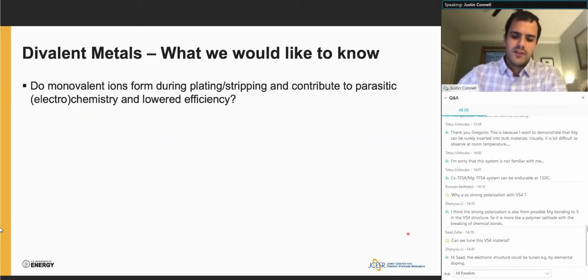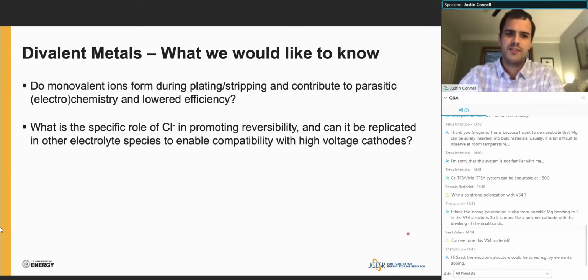Now, with all of this insight, there's still a lot of questions we'd like to answer. In particular, there's been a lot of theoretical evidence that monovalent ions form, but thus far we haven't really been able to show experimentally that they're actually present. So we'd like to know, do these monovalent ions form and contribute to parasitic electrochemistry, resulting in lower efficiency? In addition, we'd really like to know, what's the specific role of chloride in promoting reversibility in these systems? And most importantly, can we replicate it in other electrolyte species so that we can enable compatibility with high voltage cathodes? Because obviously chloride is incompatible with high voltage oxides.